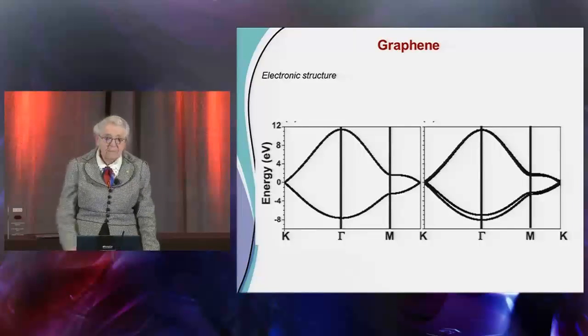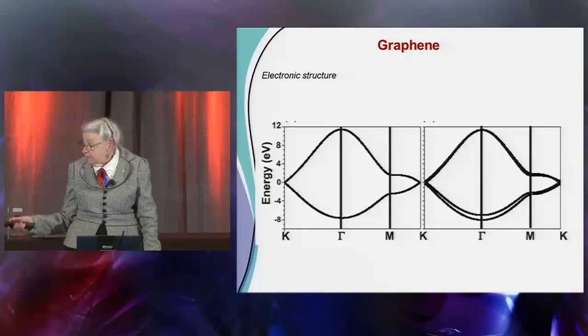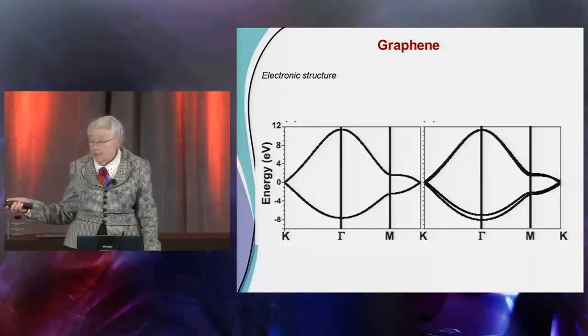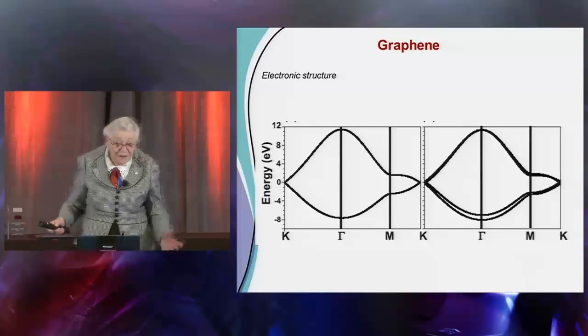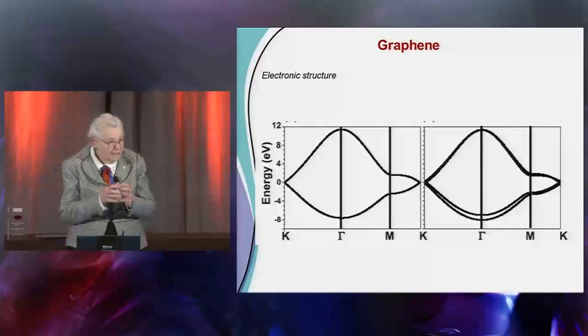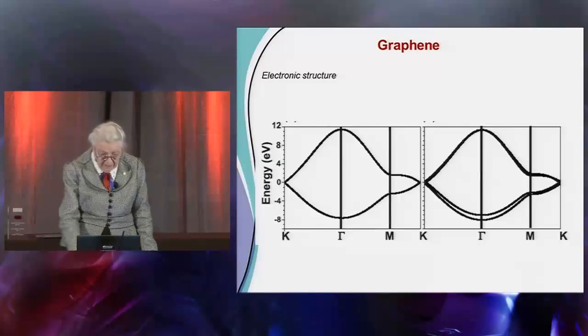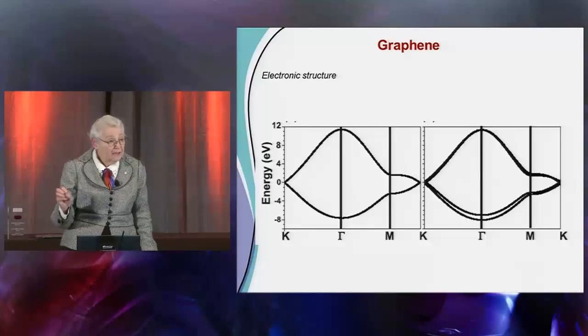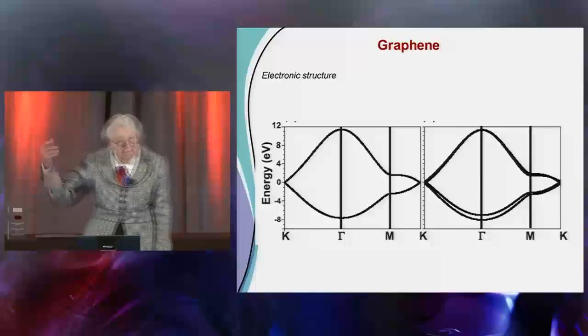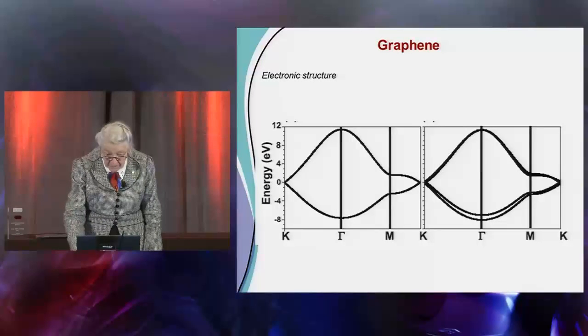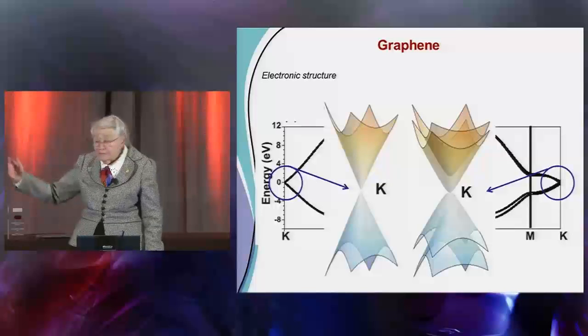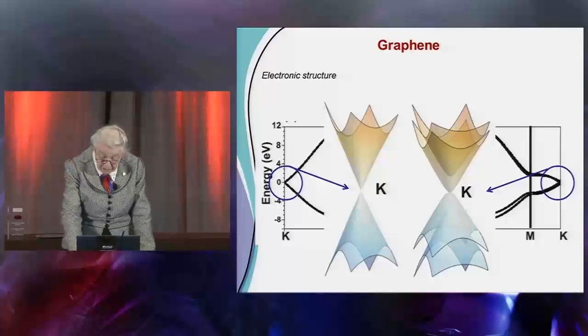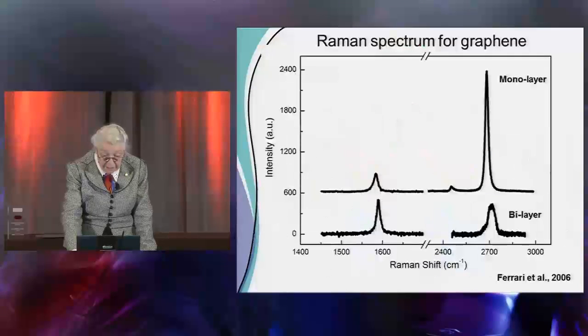So single and double layer, monolayer and bilayer, in the big picture, large wave vectors look almost the same, but on a small scale, where the Fermi level is right here, one layer gives linear E versus K, and two layers give quadratic. So when you look at it on the small scale, they are very different. And if you have very few carriers, carrier density in the system is low, so you stay very close to the Dirac point, so it makes a difference. And so we have something like that as for the dispersion relations for the single and bilayer graphene.